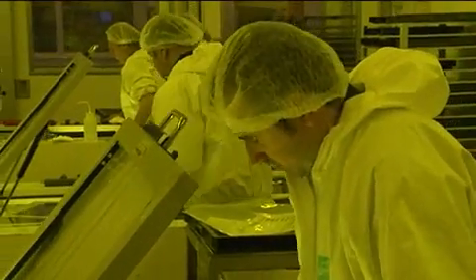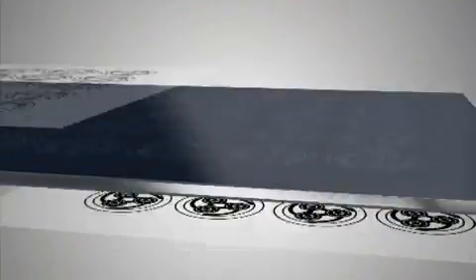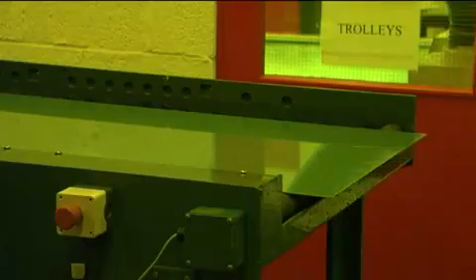The metal sheet is sandwiched between the photo tools before exposure to a burst of ultraviolet light, which hardens selected areas of the laminate into an acid-resistant surface. The sheet is developed, and any unexposed laminate is washed clear.